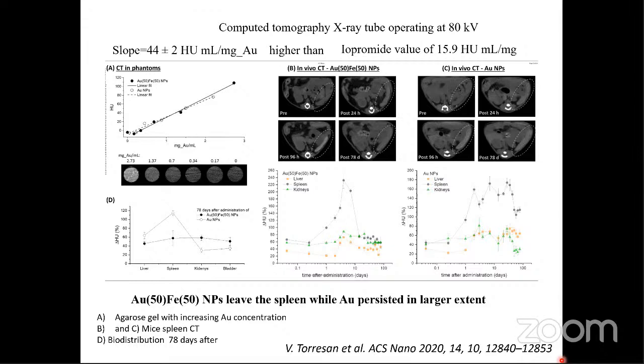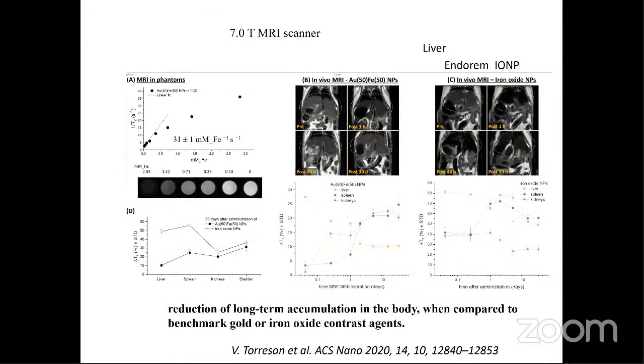The nanoparticle has also been analyzed for MRI in an MRI scanner. Here we see the phantoms: where we have much iron, we have a dark color. If we don't have iron, we have a gray color. In the images, the colors change in a way that indicates the iron is getting out of the nanoparticle, as we already saw in vitro. We can compare with ENDOREM, and in ENDOREM you see that there is no change in color like happens in the iron-gold nanoparticle.